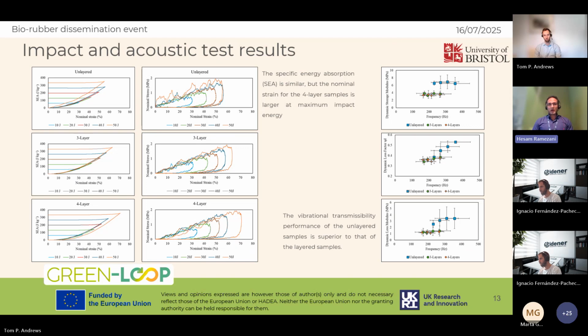To evaluate the impact and acoustic properties of the rubbers, we performed other tests. And as you can see on the left-hand side, we have the specific energy absorption versus nominal strain and nominal stress versus nominal strain. So between 10 joules and 40 joules of impact energy, basically every sample had the same performance. But it gets interesting when we reach the 50 joules.